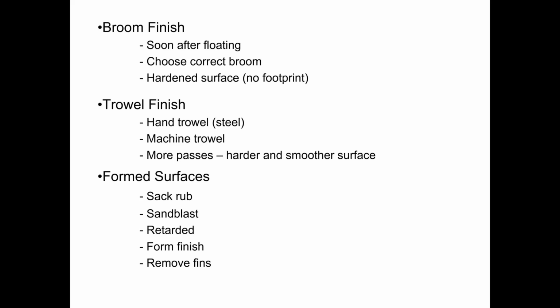And then of course with retarded or exposed aggregate surfaces, we can use a retarder to retard the set of the matrix on the surface, and then we can pressure wash that matrix away shortly after the product has been stripped from the form, so that we expose most of the aggregate on that surface. And depending on what type of aggregate we're using, we can have a very beautiful finish that could be multicolored, or there's a lot of different color aggregates that can be used. So retarded is one of the most common architectural finishes that's been around for so long, just because you can achieve a good uniform finish that architects like.